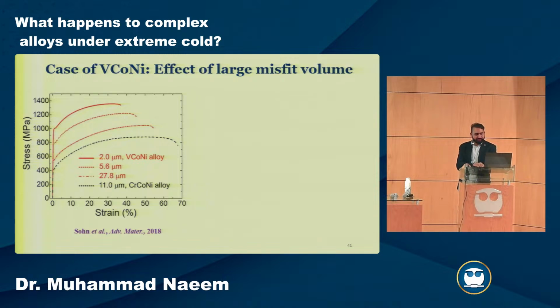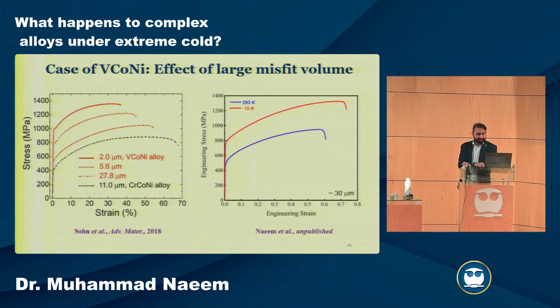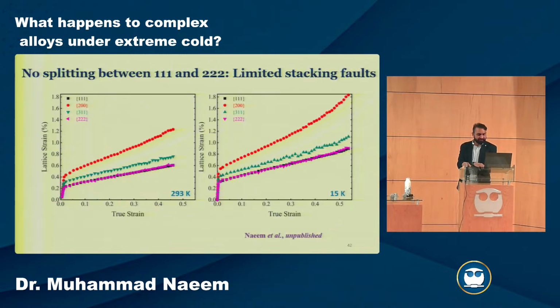But then there was this report about vanadium, cobalt, nickel, where vanadium has a much larger size and much higher misfit volume, and it can have much higher yield strength because of that. So we were very interested in that material, and we used one with a not that fine grain size, a bit coarser grain size, and it also showed an increase in strength and ductility. But it was very peculiar for this example.